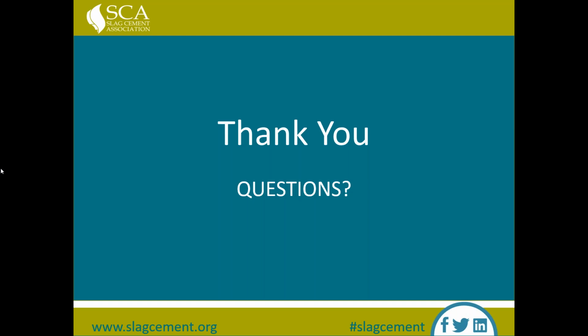Another question for you. Please give a short brief on thaumasite. Well, again, I wasn't sure of my audience, but my understanding is that if you're in the northern reaches of Canada, Scandinavia, places where you have very sustained cold periods without temperatures getting much above freezing, you end up with this phenomenon that is thaumasite. And thaumasite is almost like a carbonation attack. It's actually slowly reversing the process of calcium silicate hydrate or the calcium aluminate component of it. And so you end up with something that you can sit there and rub dust off of the exterior of it.